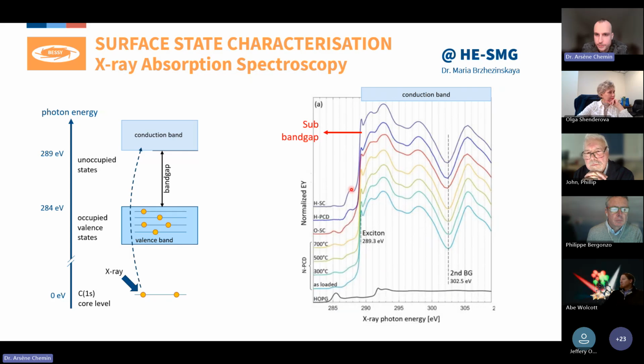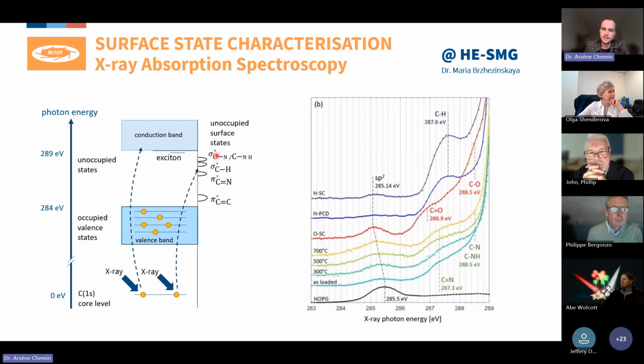289.3. And I realize I actually don't have my pointer on. Yes. So here you have the exciton, this peak here. And everything below that actually corresponds to excitation of surface states. That is very nice because by doing X-ray absorption at the synchrotron, we are able to find out where in the band gap those surface states are.